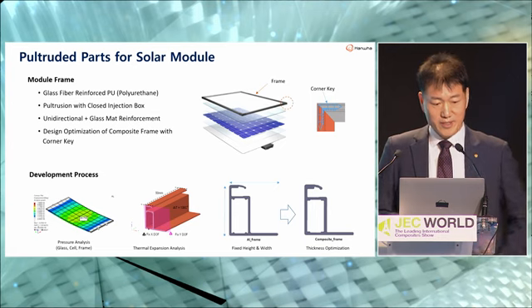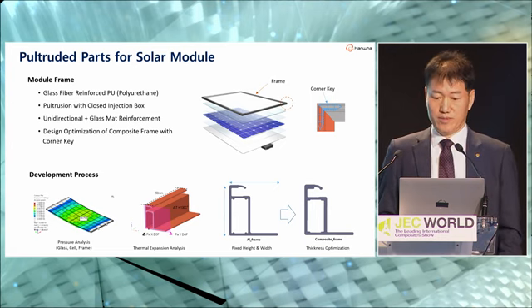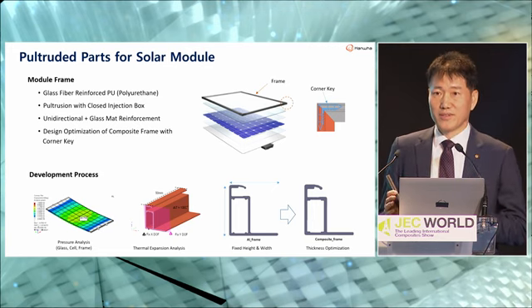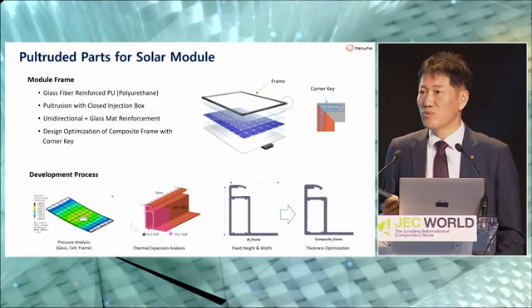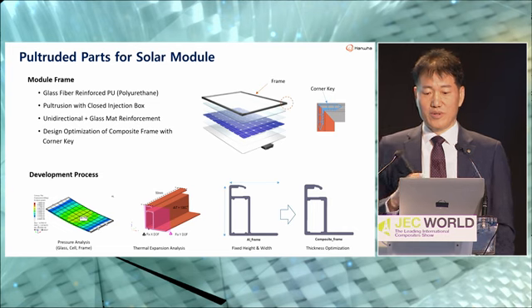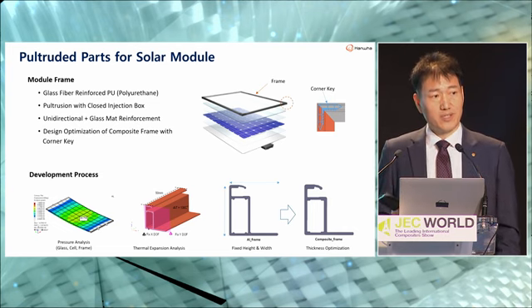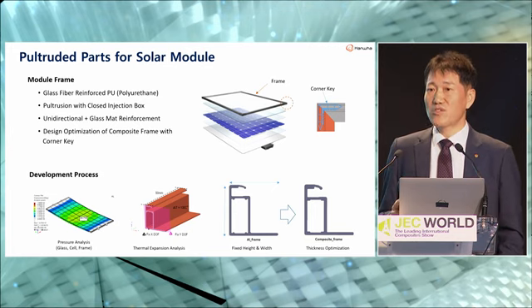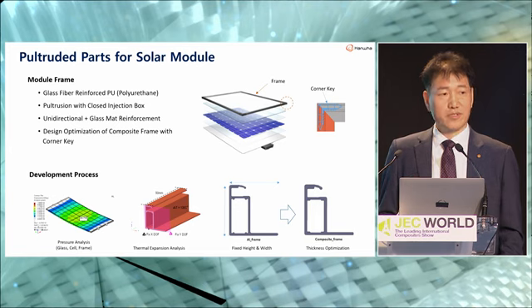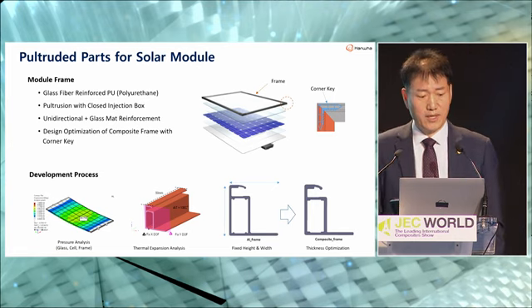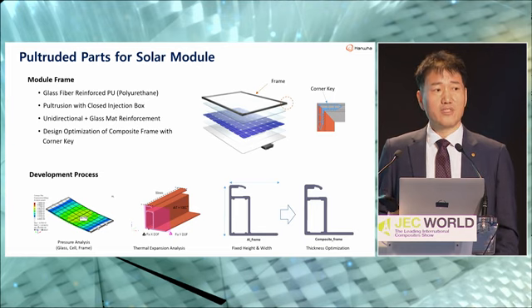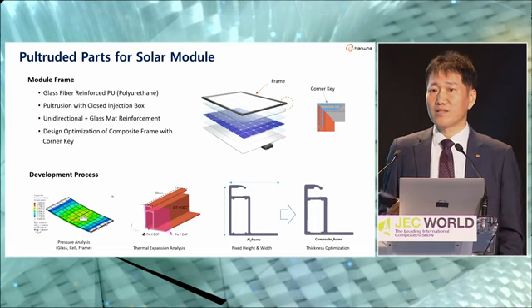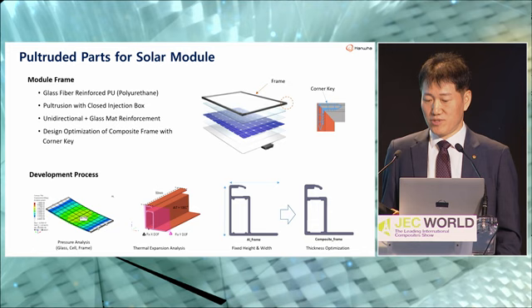The last one is a pultruded part for solar modules. There was a demand from our customer to replace the aluminum frame with a composite one. We made the decision to apply pultrusion as a molding technology because it can form a continuous fiber reinforced three-dimensional profile. We considered polyurethane as a base material instead of epoxy to reduce the material cost. And we also considered a closed injection box to get better impregnation of glass fiber during the process.